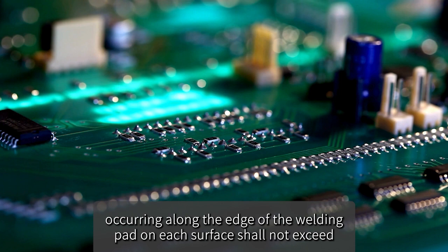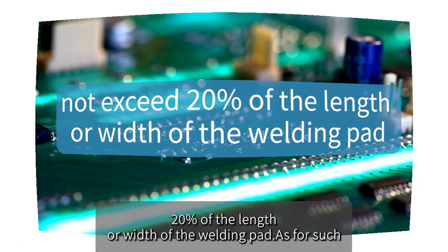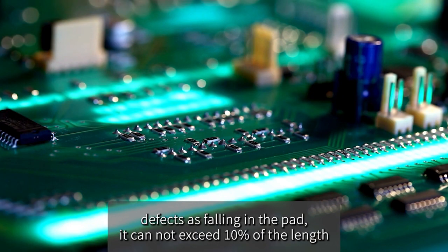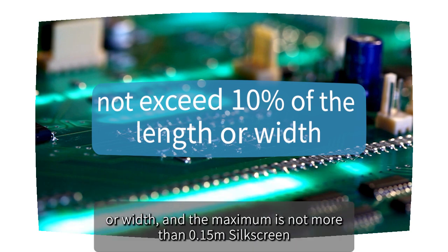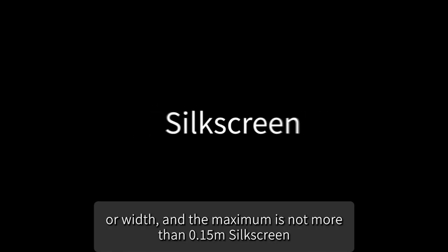occurring along the edge of the welding pad on each surface shall not exceed 20% of the length or width of the welding pad. As for such defects falling inside the pad, they cannot exceed 10% of the length or width, and the maximum is not more than 0.15 mm.